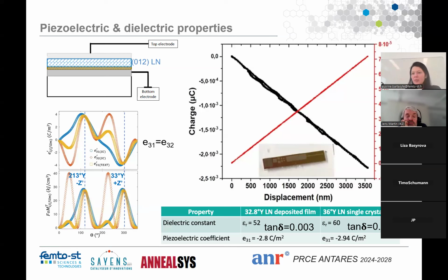So we measured this e31 coefficient, and basically it was very close to that measured with the same technique on Y36 oriented lithium niobate, say single crystal films. And we measured the dielectric constant. Of course, you need to be very precise on the thickness to tell exactly, but it seems to be a little bit lower, the dielectric constant, than that of the bulk. But the tangent loss is the same. So it's on the order of 10⁻³.